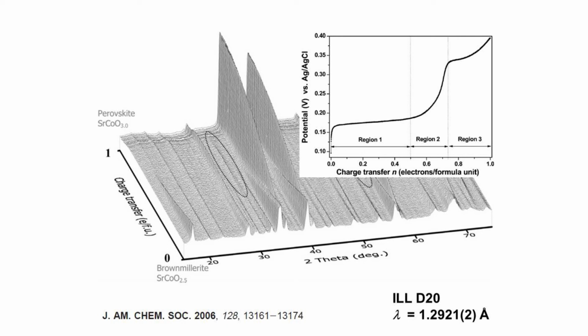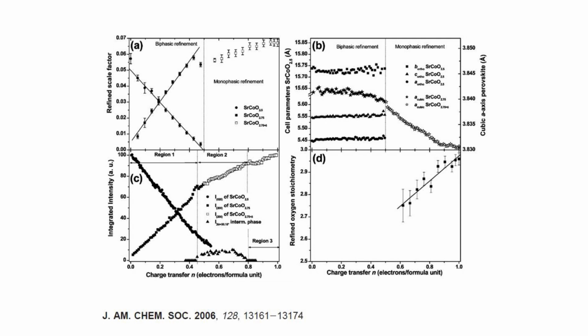Then the potential changes importantly here, and here we reach, this means that in this case we have only one phase, and this phase is changing. This means that moving from strontium cobalt oxygen 2.75 to strontium cobalt oxygen 3.0, we have the same phase in the whole solid that progressively changes. So this is better seen maybe in the result of the Rietveld refinement.